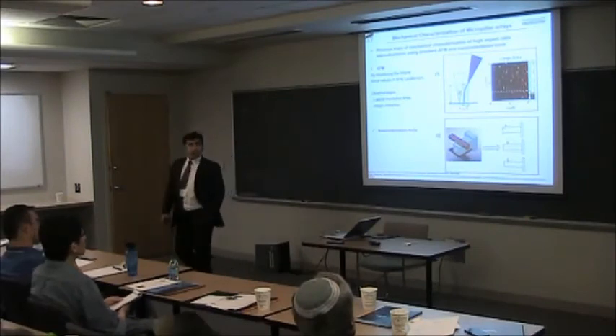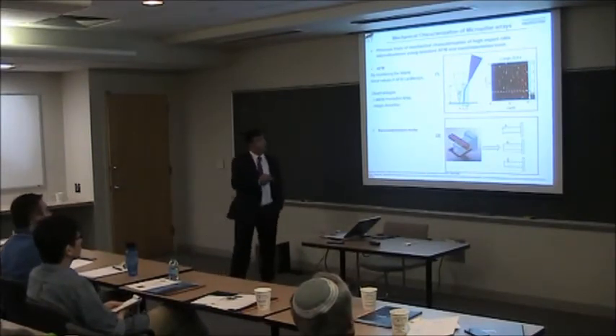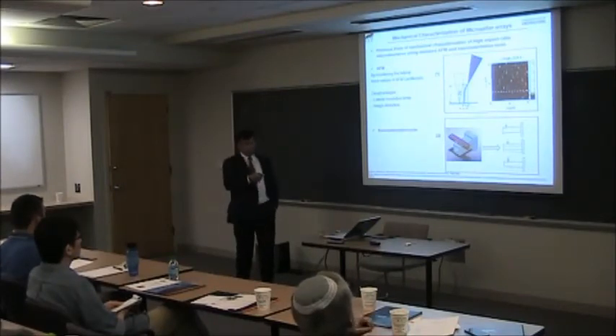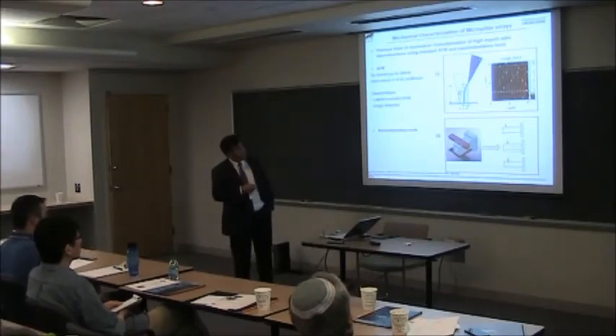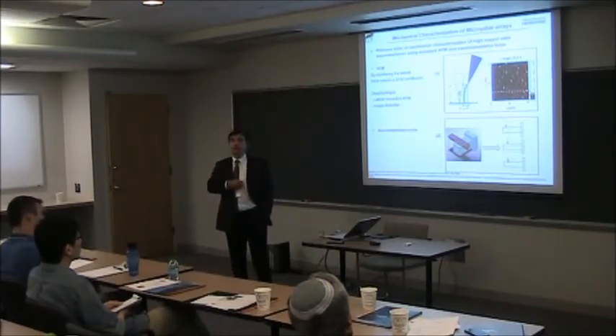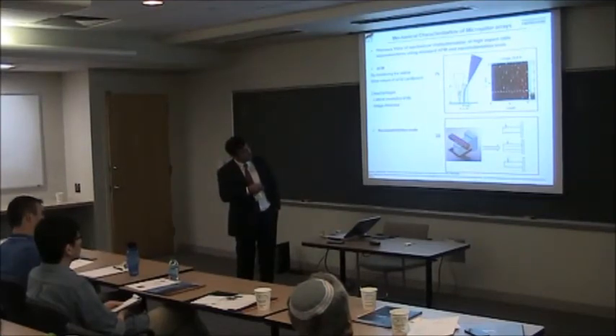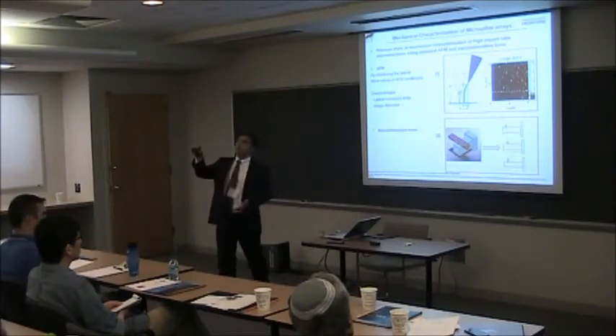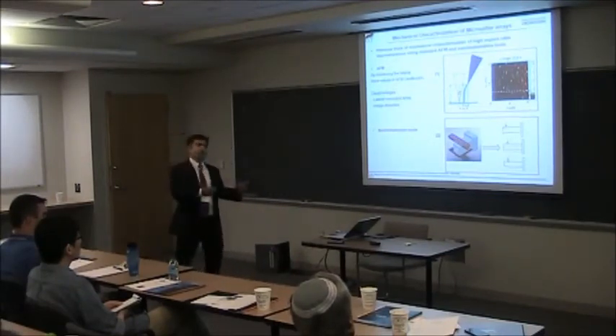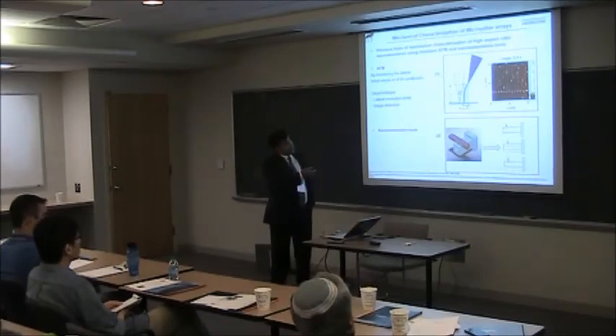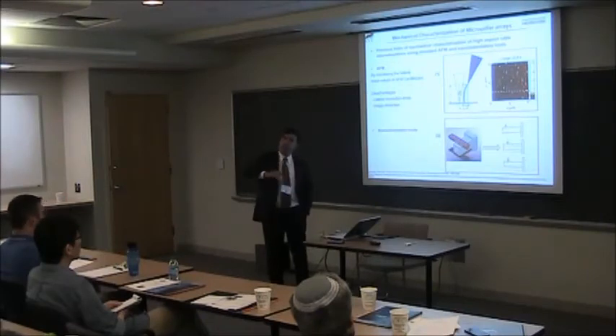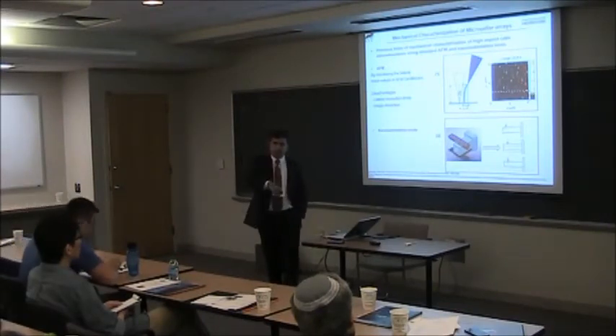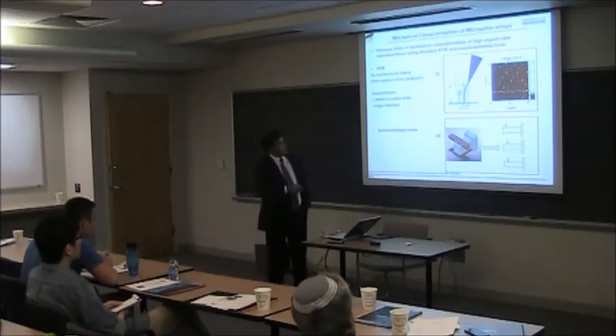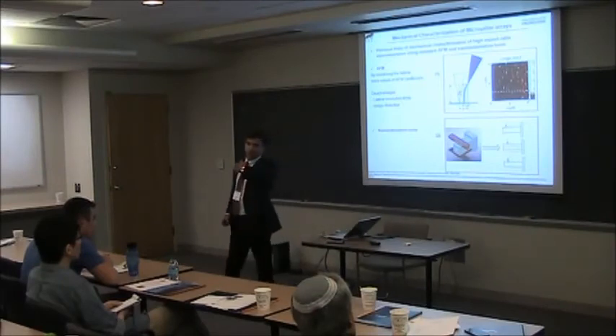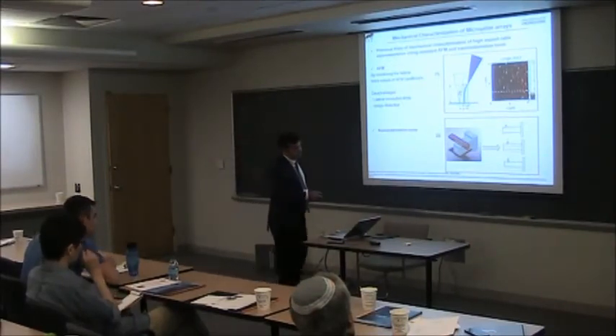Now, obviously a lot of people are doing similar work. AFM tips basically do the same thing, right? There are papers where you use an AFM tip at an angle, you come to the pillar and pull it a little bit, look at it from the camera, measure how much the change in X is, and based on the height, you can guess the curvature. Using the curvature, you can backtrack the Young's modulus. And obviously, this has issues in terms of pulling forces. You don't know exactly how much force you're applying, because the AFM tool is designed for downward push, not pulling. And there are other methods where you turn the pillar 90 degrees and then push on top, which also has some issues regarding deformations.